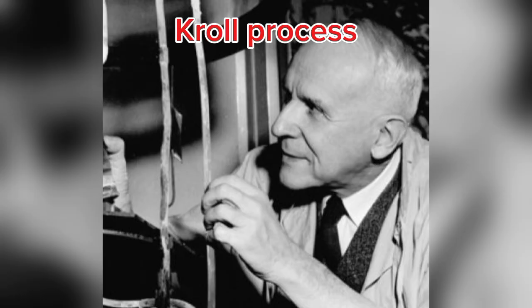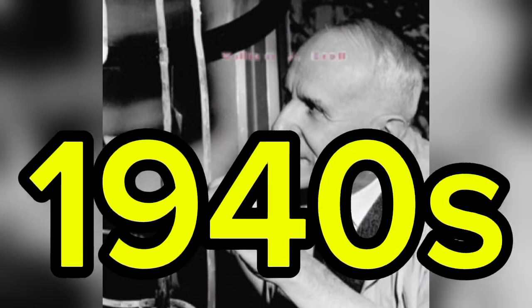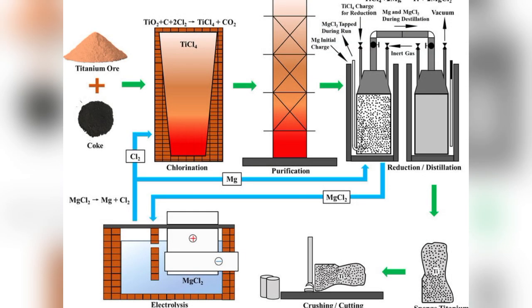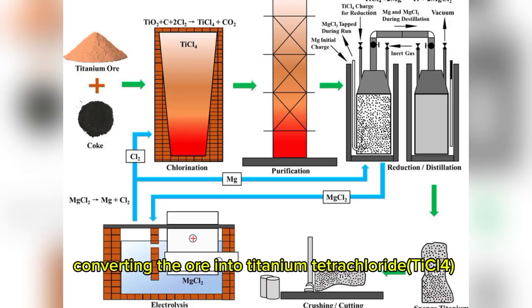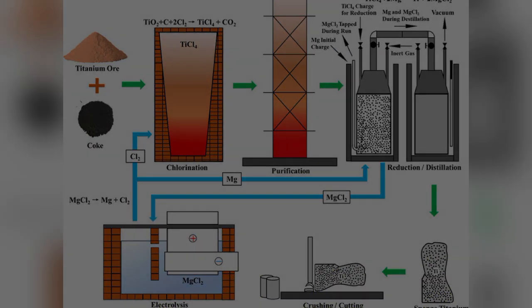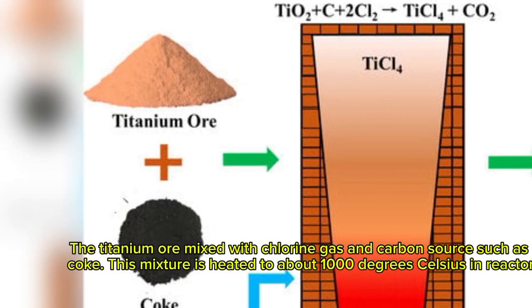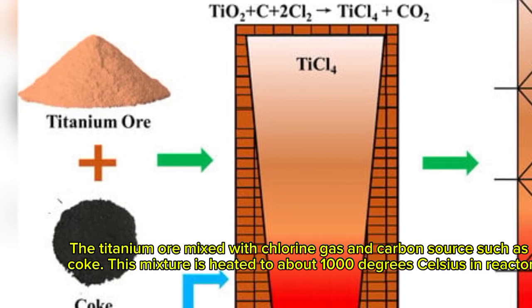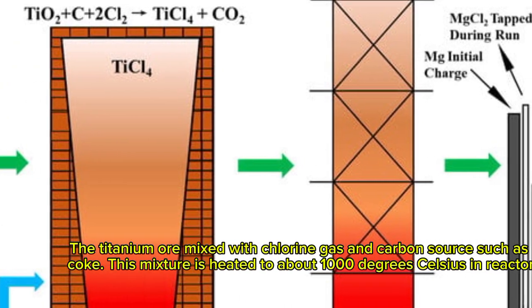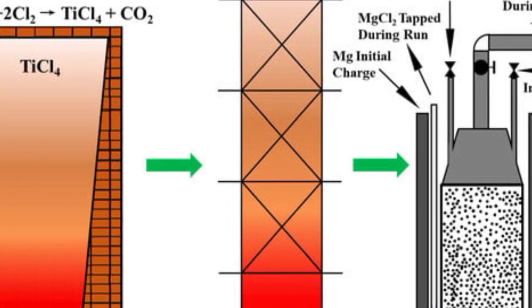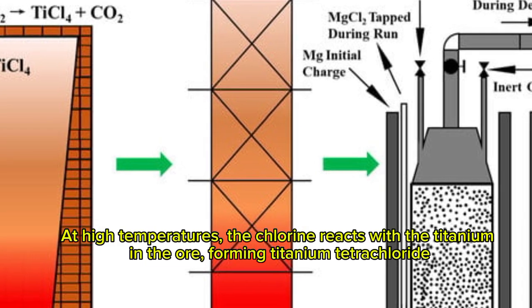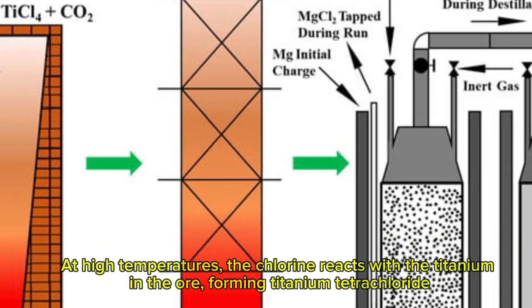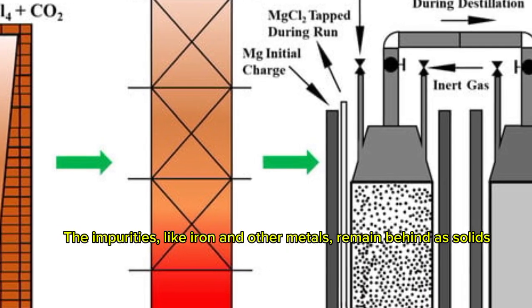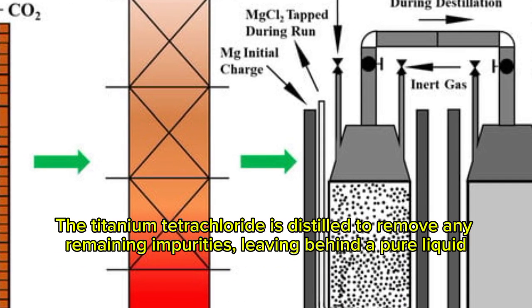The most common method is the Kroll process, developed in the 1940s by William J. Kroll. The first stage involves converting the ore into titanium tetrachloride, a volatile and highly reactive liquid. The process begins by mixing titanium ore with chlorine gas and a carbon source such as coke. This mixture is heated to approximately 1000 degrees Celsius inside a reactor. At high temperatures, chlorine reacts with titanium in the ore, forming titanium tetrachloride, while impurities like iron remain as solid residues. The titanium tetrachloride is then purified through distillation to remove any remaining impurities, leaving behind a pure liquid.